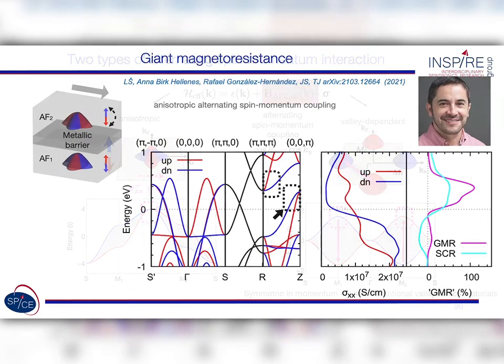And there is this idea that you can go into creating giant magnetoresistance devices, where you essentially flip the polarization by reorienting the Néel order in one material relative to the other, creating very large GMRs, as observed in ferromagnets. Here the challenge is, of course, how to reorient these two Néel order parameters so that you have these 180 degree domains between them. So for multi-domain samples it would be challenging to do.